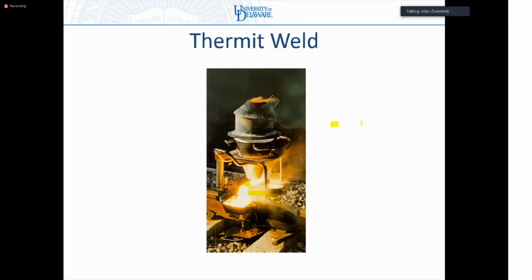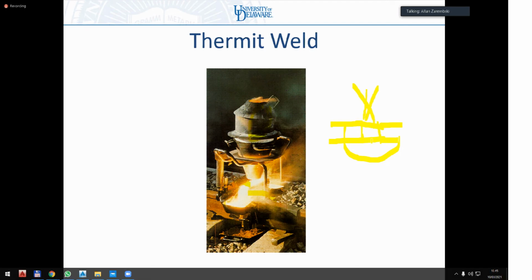So in a thermite weld, you basically have a gap between your two rails. You put up some molds in here, and then you pour molten steel from the thermite process, which, as was indicated in the movie, is an exothermic process which generates heat. So you have this very hot molten steel pouring into this gap, filling this gap, and then you let it cool, and then you have to grind it down to match the shape of the rail. That's the thermite weld process.